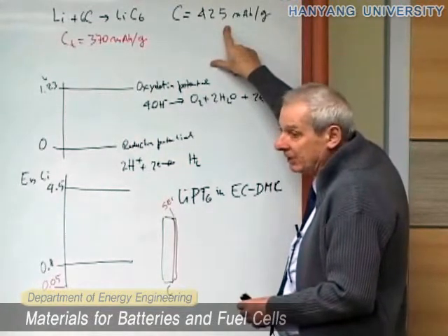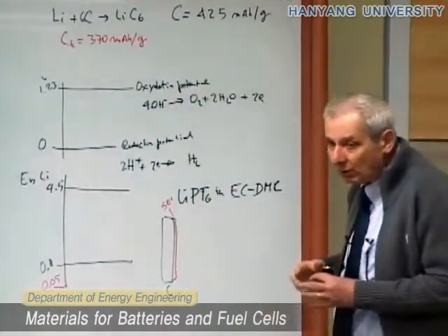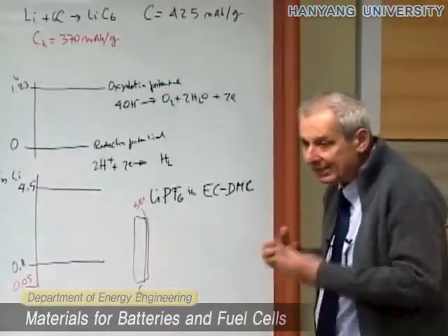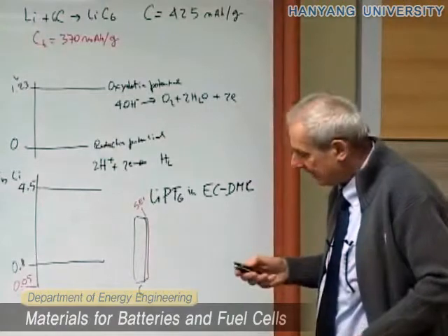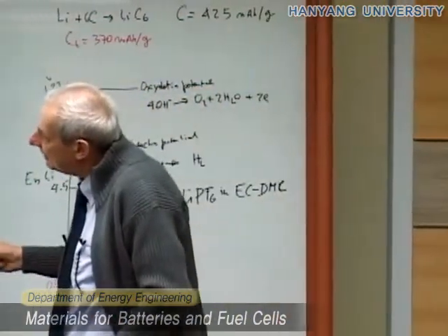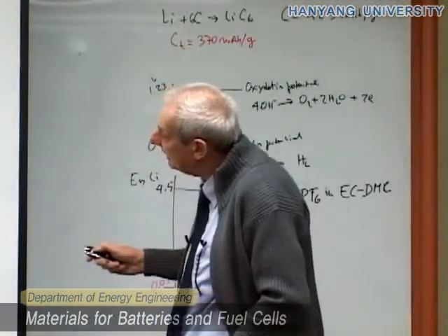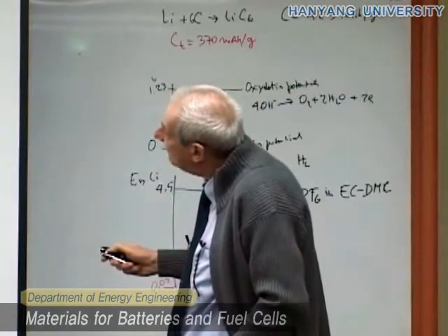Actually, what maybe happens here is that this higher value is due not only to the electrochemical reaction, but to something else which apparently gives a higher capacity. And this something else is the capacity, the charge necessary to decompose the electrolyte. In fact,